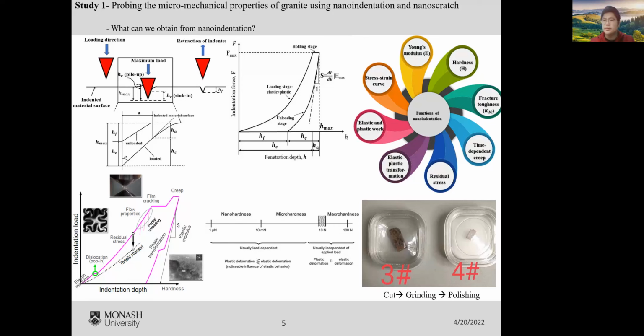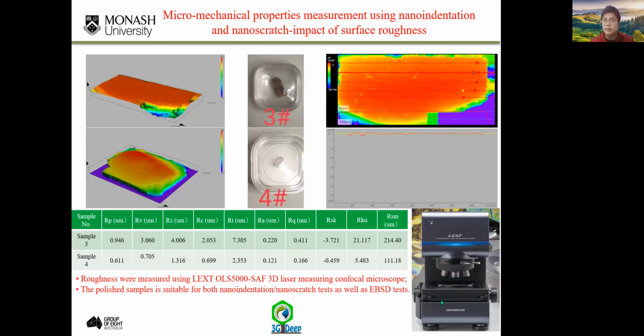Because nano-indentation is a high-resolution technique, the sample size is quite small. Therefore, we have to cut our sample, grind our sample, and then polish our sample. After the polishing, we need to measure the surface roughness of our granite sample, and we have to make sure that our sample is suitable for both nano-indentation at the nano-scale, as well as the EBSD test.